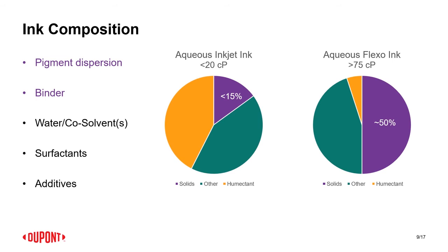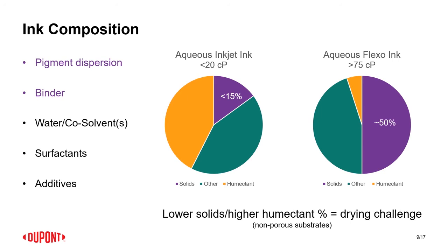The other key thing is to pay attention to the yellow slice on the pie chart, right? In aqueous flexo inks, you have a very low level of humectant, whereas in aqueous pigment inks for inkjet, we tend to have a very high level of humectant, and the obvious reason for that is because as you're printing, you don't want your ink to be so fast drying that it's drying on the print head nozzle, right? Because then you're going to have a terrible printing performance. And so typically you put a lot of humectant in there in order to have good printing, but now on these non-porous substrates, you need to be able to remove the water, and the whole point of a humectant is to retard drying, right? So you have that challenge that you then need to meet when you're looking at these non-porous substrates.